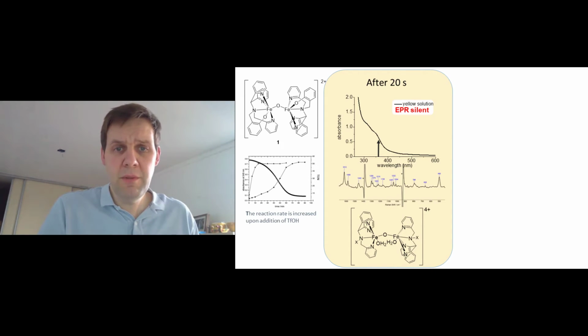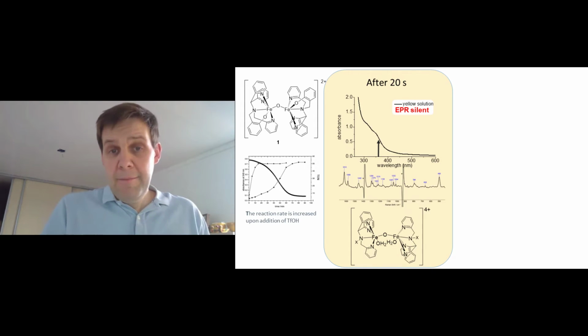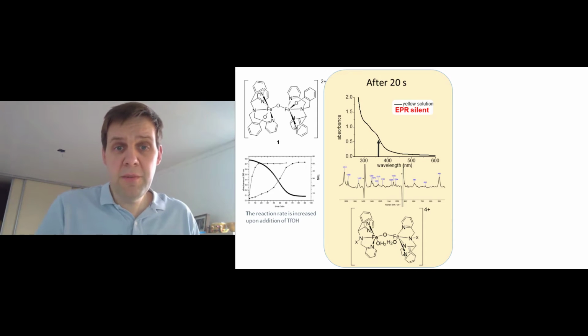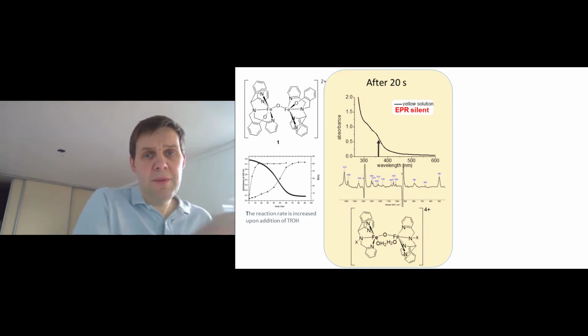And when we do that, we run a Raman spectrum at 355, which you see below the absorption spectrum. That actually corresponds to something we looked at before, which is a very similar complex, which doesn't have these phenolate units, and it's a bit boring. And this is a relatively unreactive iron dimer. So this is what appears 20 seconds after the reaction starts.